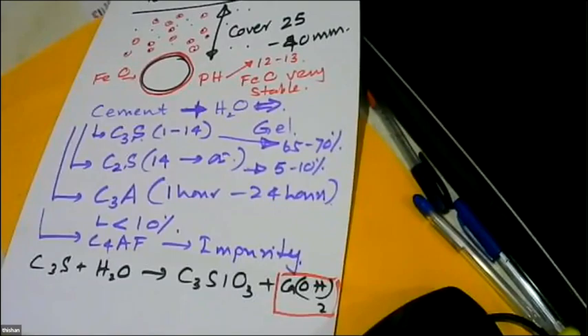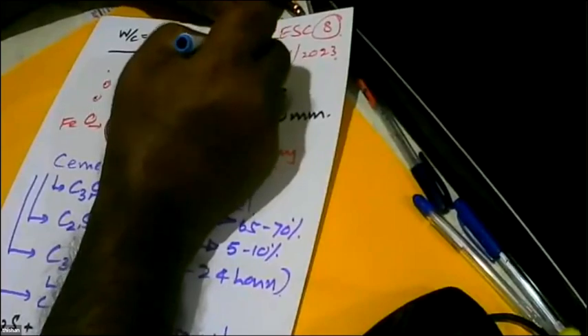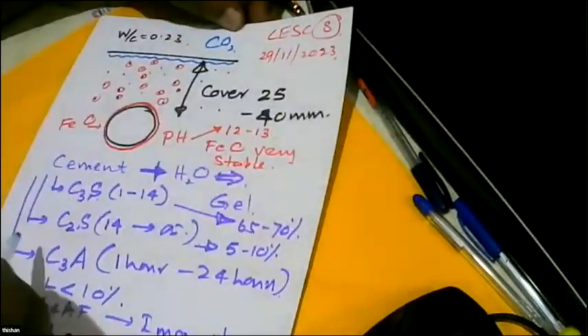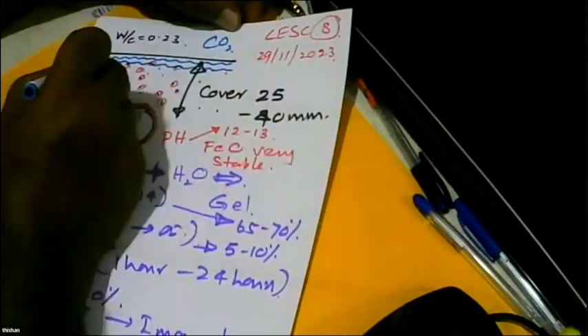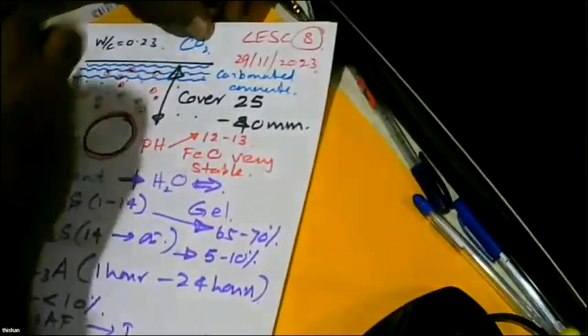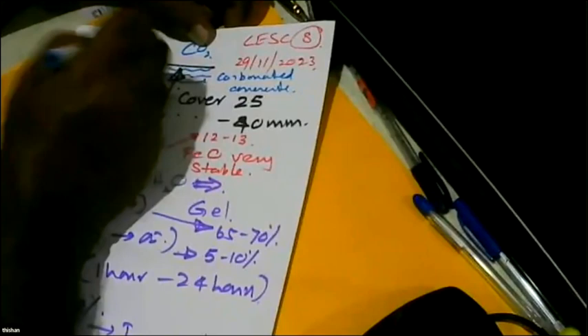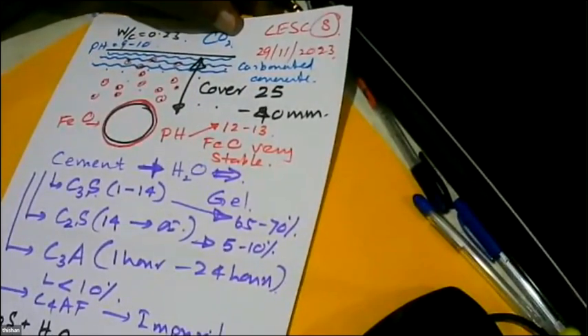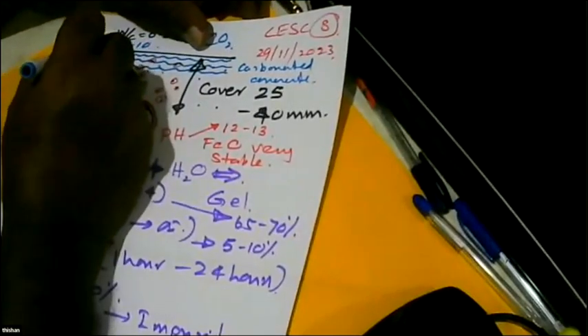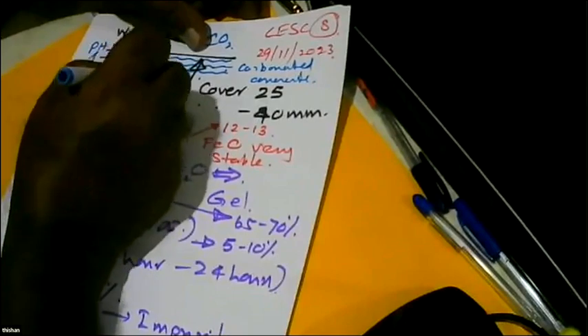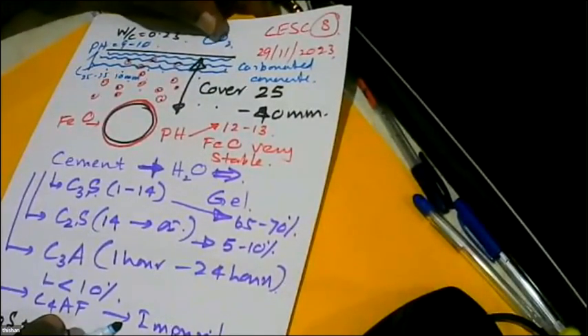But what happens with time? We have carbon dioxide in the atmosphere. This carbon dioxide will start reacting with calcium hydroxide and gradually form a calcium carbonate layer. And that is called carbonated concrete. So what is the problem? Carbonated concrete pH can be around 9 to 10. And that means it's not stable. When pH is 9 to 10, it is not stable, but still it will take plenty of time. In well-cured concrete, for about 25 to 35 years, you might get only 10 millimeters of carbonation. But if you don't cure it well, even in 10 years, you might find the carbonation can be 10 millimeters.